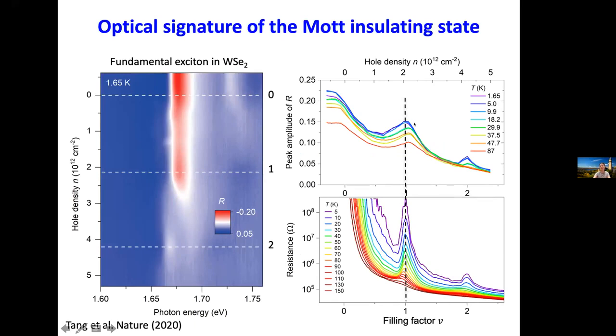you can also see this feature in optical absorption. What I'm showing here is the absorption spectrum of the fundamental exciton as a function of hole density, and you see this bump right at filling equals to 1, and this is correlated with the peak in the transport.